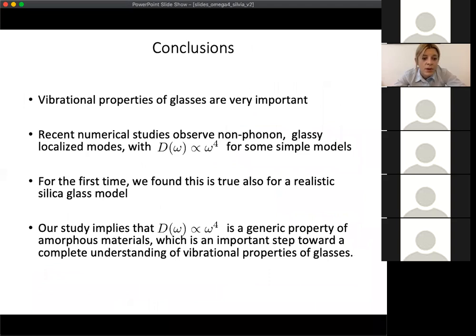We can see the signature of the extended phonon modes that start to enter in the bigger system, so we focus on the smaller system size. These were our main results. Let me conclude. The vibrational properties of glasses are very important to understand also other basic features of glasses such as dynamical, thermodynamic, and mechanical properties. Recent work observed this non-phonon glassy localized mode with D(ω) proportional to ω^4 for simple two-body interaction models.